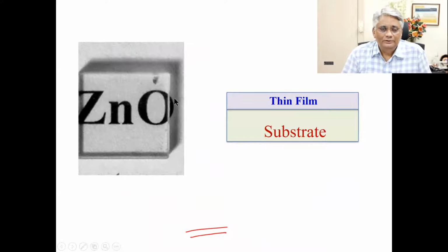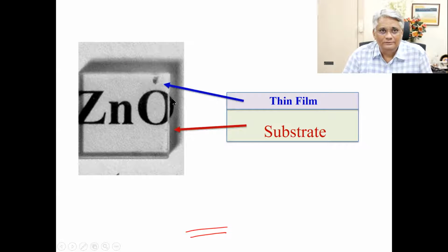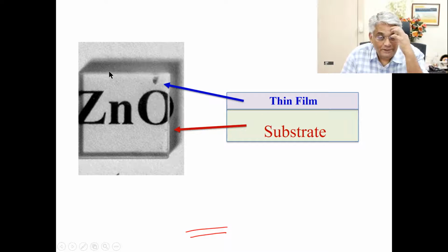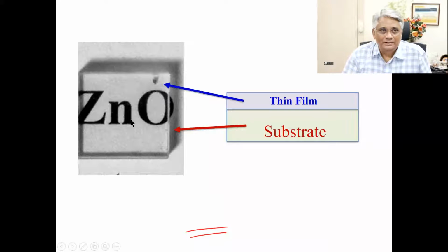To continue with that example, look at this nice example. I told you I have a small glass slide. Glass, of course, is insulating. And so a thin layer, about 60 to 70 nanometers of zinc oxide is coated on it. So the transparency of zinc oxide is also as good as that of glass. So just see through. The coated film on a substrate is kept on these three letters printed on a paper. So you can clearly see the transparency of the film, along with glass, of course, which we know is transparent. Okay.